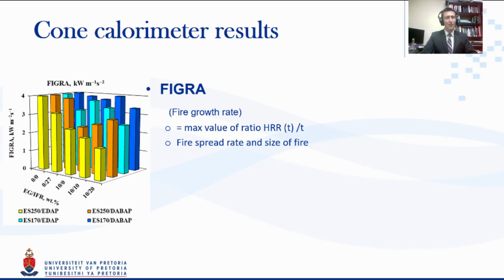And once again, we found a really good result. We found that the neat materials improved the FIGRA, but that their combinations far exceeded those. In fact, so much that it really exceeded our expectation, leading us to think that there was somewhat of a synergistic effect between the two different intumescent behaviors. Because here at 10-10 loading, there is a lot less of the EDAP or of the DABAP, but they both improve upon any of the materials on their own.